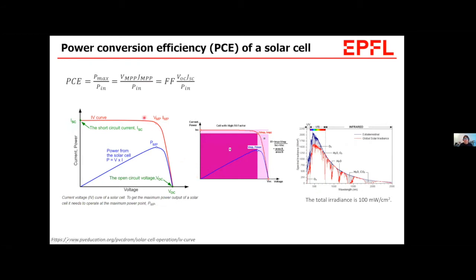And how we estimate the efficiency of perovskite solar cells, this is the definition of power conversion efficiency. This is the power max, power out divided by power in. And this power in is related to the solar spectrum here. The standard we use to simulate is normally 100 milliwatt per square centimeter, so-called one sun. And the power out is correlated to the VOC and JSC and fill factor. So the JSC, the short circuit current, is the current through the cell when the voltage across the cell is zero.